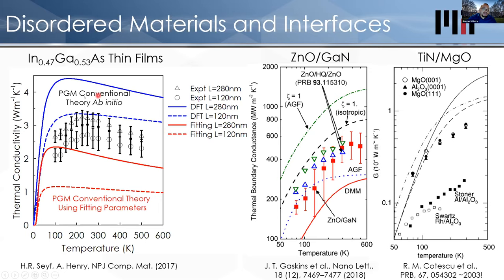What ends up happening is you see very significant deviations in the agreement between theory. Here, this is ab initio theory, again, from first principles. Now these two lines no longer agree with the experimental data here, which are the dots. And then what's even stranger is, even if you use fitting parameters, you just use the functional form that you would get from the phonon gas model, treat the mean free path as free parameters, you still can't explain the data, which is even worse, right? So even with fitting parameters, I can't get it right. This is a great hint from Mother Nature that something is wrong with our perspective.